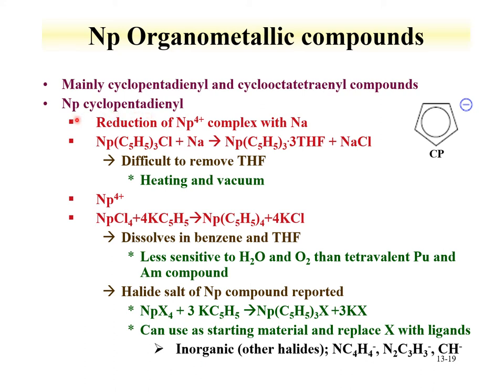The synthesis route is shown here, where you can take neptunium Cp chloride with some sodium, drive a reduction to get the neptunium 3 tri-Cp in tetrahydrofuran. It's been found difficult to remove the tetrahydrofuran from this compound, so there's strong coordination still in that environment. In neptunium 4, a similar synthesis, again with a chloride starting compound, where we can get the 4 Cp ligands around the neptunium. This dissolves in benzene and tetrahydrofuran and could allow spectroscopic examination of this material to be performed.